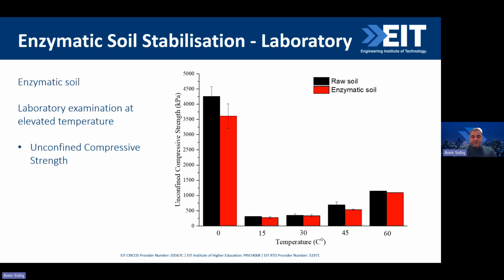Then, based on the unconfined compressive strength at the different temperatures, we can see the enzyme is having a reduction compared to the raw material. But at 15 or 30 degrees, it is almost consistent with the raw material. At 45 and 60, it slightly reduces. A couple of issues could be because soil is not a consistent material, it's a non-homogeneous material, so it could be an issue there. However, even though the strength is slightly reducing, we got the cost saving of the water and the strength development. And we're going to go through the next slides on the behavior of the enzyme protecting the clay particles, which is much more important compared with this very small strength reduction.